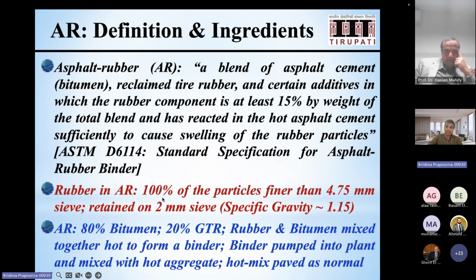Okay, so 100% of the rubber particles are finer than 4.75. Some of you are familiar, I'm sure, 4.75 is the benchmark between coarse aggregate and fine aggregate. Anything beyond 4.75 is a coarse aggregate, less than that is fine, right? So we are looking at a specific gravity of about 1.15 for the tire crumbs. That's close to the binder specific gravity. 1.01, 1.02 is what we see with asphalt cement.